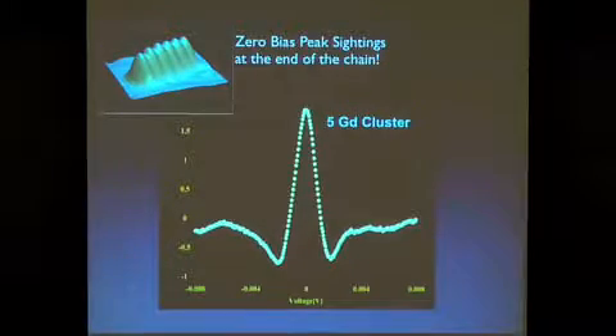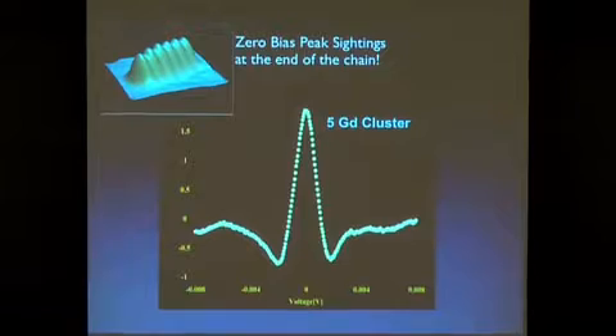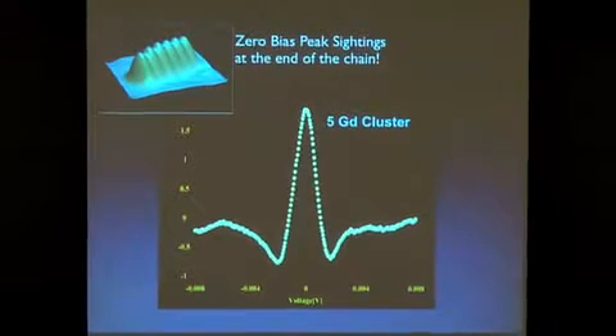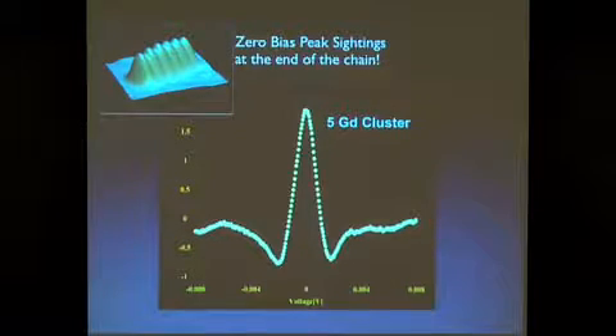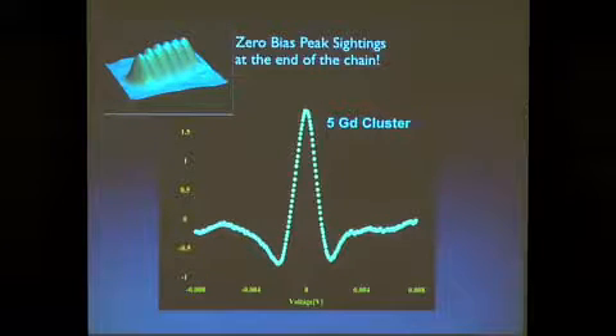So we just did this experiment. We just made gadolinium chains, yes, and we find a strange effect, which is that in the middle of the chain there is a gap. On the edges there are these peaks. So we don't have any spin information about what the spin is doing here. So this could be anything, but it's very promising because it lives at the end of the chain. But the calculations you showed, you already had a spin pointing.